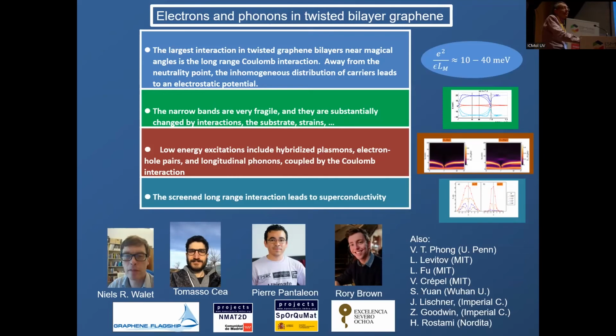First, twisted bilayer graphene is a very interesting material indeed. Second, the largest interaction in twisted bilayer graphene is the long-range Coulomb interaction, and this is a simple estimate of how strong it is. This is the size of the moire, and this is the kind of self-energy of a quantum dot of that size with one electron in it. That means that the bands, which initially are narrow, stop being too narrow and are changed in a significant way by this interaction.